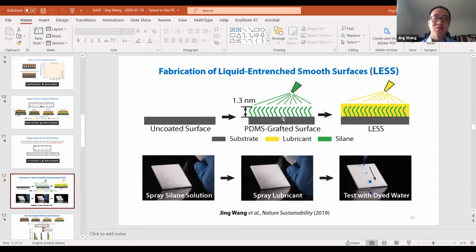But for the longevity, we do observe, not on the toilets, but on the windshield, over not half a year, over years, that it still degrades. We don't know the mechanism right now, because PDMS should be stable under UV, and we are using brushes made of silane. So we don't know the mechanism of this degradation, but we think there are some drawbacks of using this one. There's some room to improve. We need more investigation on this.